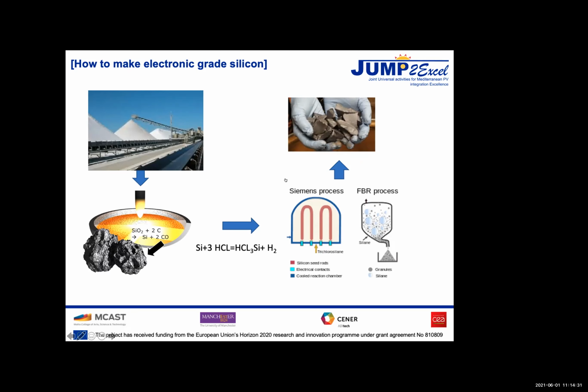So the main detraction from silicon, at least philosophically, is that it's a high energy, high temperature material. You have to smelt it with carbon in the same way as you do iron. That produces what's called metallurgical grade silicon. So first of all, you mine it somewhere. That's straightforward. Silicon makes up 27% of the Earth's crust. There's plenty of it around. We can find it on the beach or the desert. We select a source of silicon which is low in impurities, because that helps from the beginning.